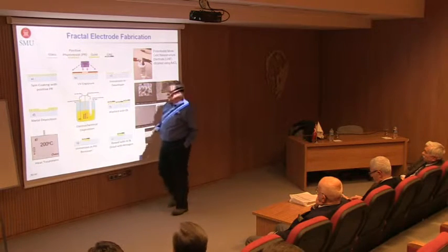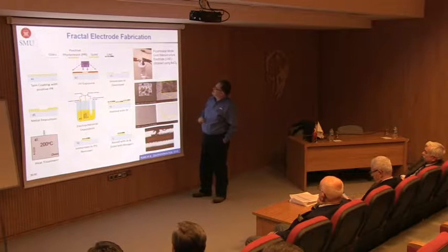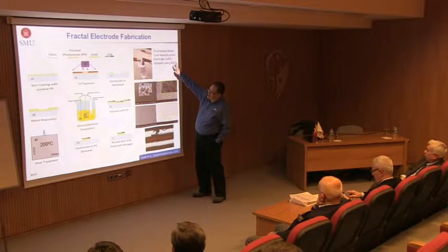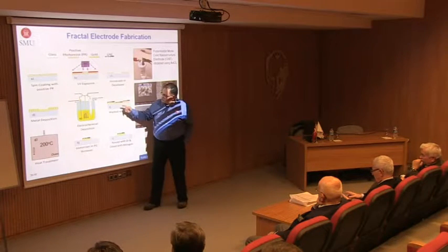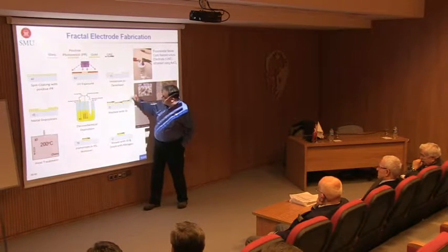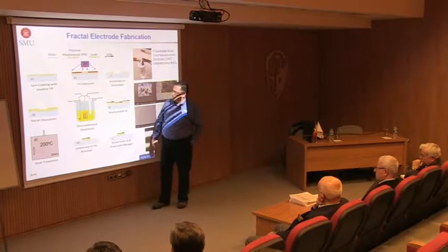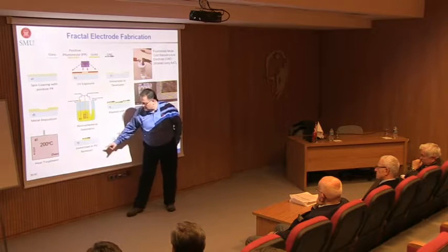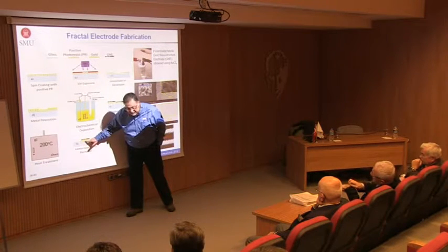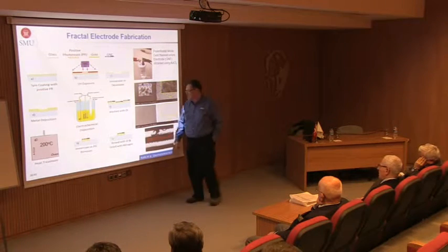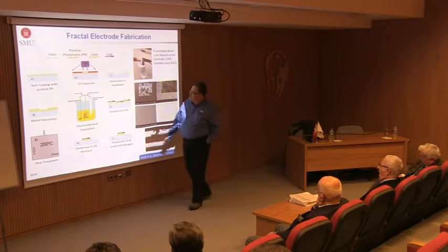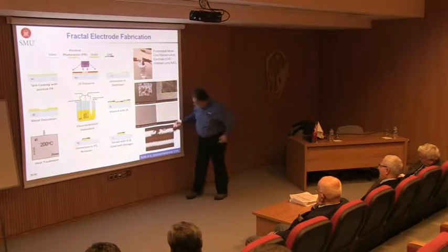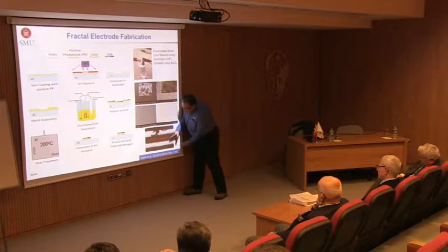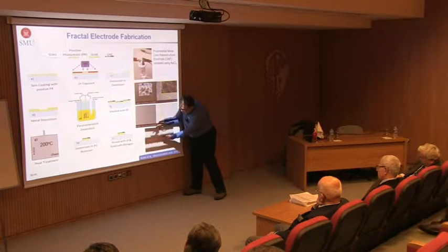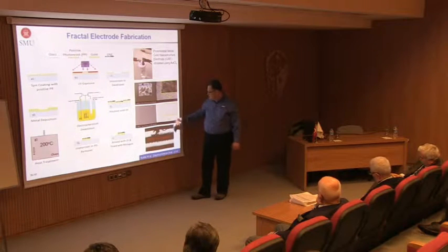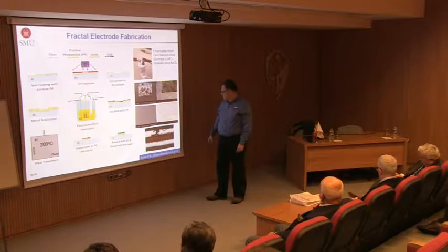But at this stage, we do electrochemical deposition using the potentiostat mode, and we actually cover things with gold nanostructures. And everything basically grows on all the gold, because this is conductive, and everywhere now I have nanostructures, and we bake it, and then we immerse it in PR remover, and now we have the gold portion that I'm interested in that has only the fractal structure, which you rinse and dry. If you do not use this mask business and do it this way, then you end up growing fractal structures all over, and when this is positive, when this is negative, and so on, they basically create a useless electrode, because now you have a problem.